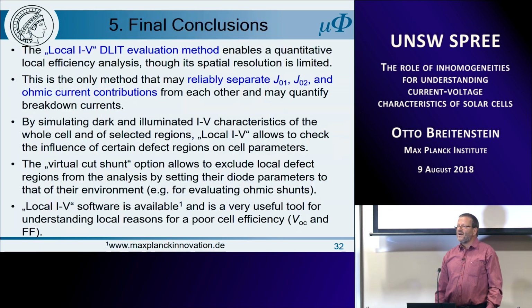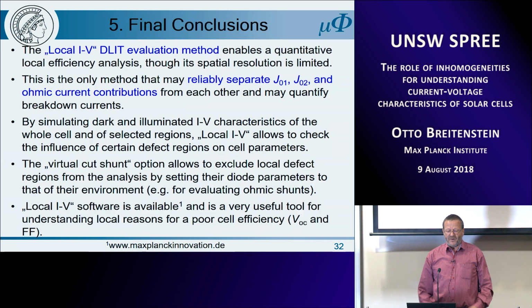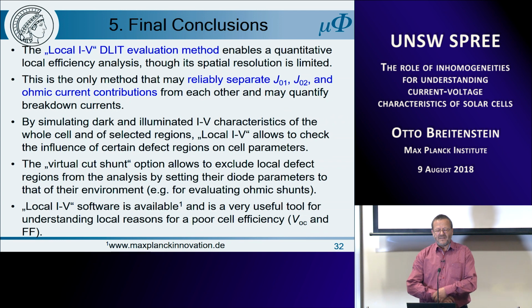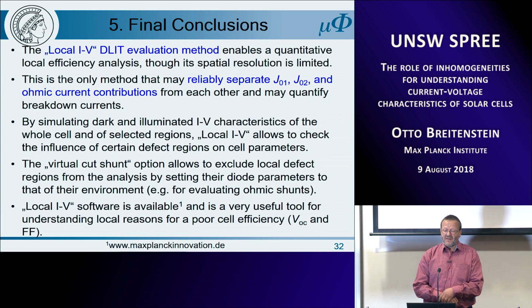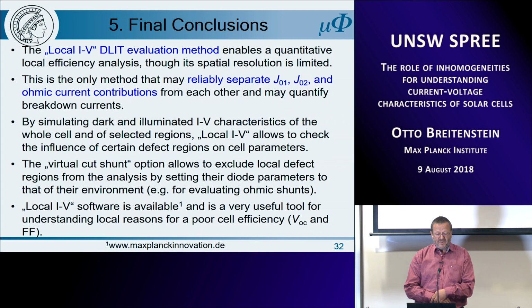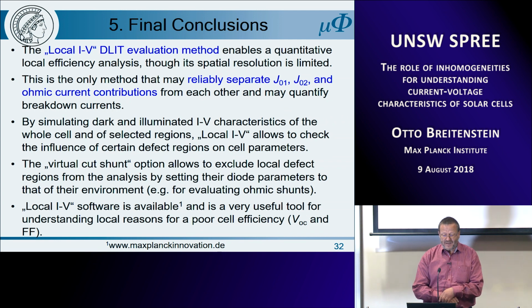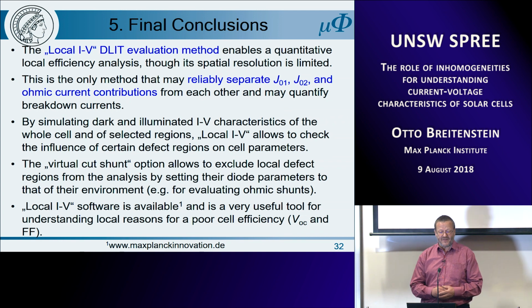This brings me to my final conclusions. So the local IV dark lock-in thermography evaluation method, which was used in the first part of the talk, enables a quantitative local efficiency analysis, though its spatial resolution is limited. And this is the only method that may reliably separate J01, J02 and ohmic current contributions from each other and may quantify also breakdown currents.